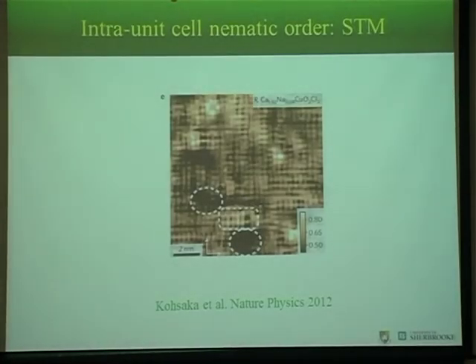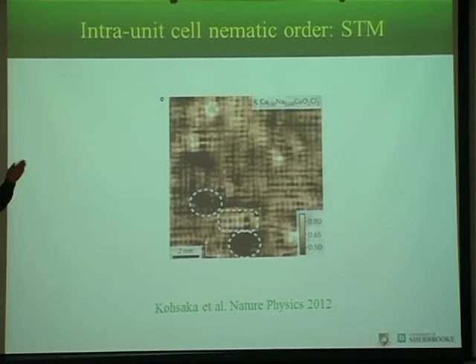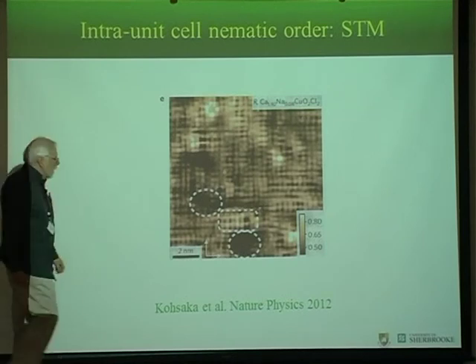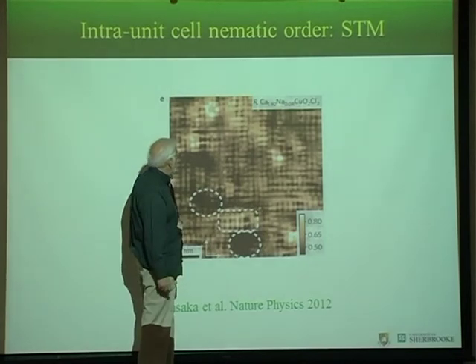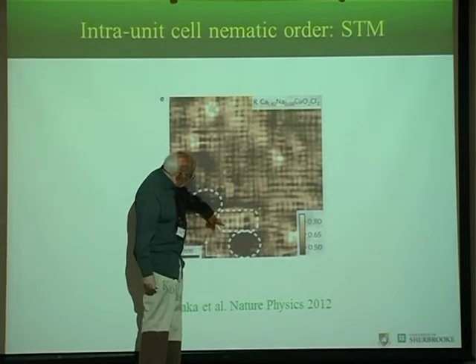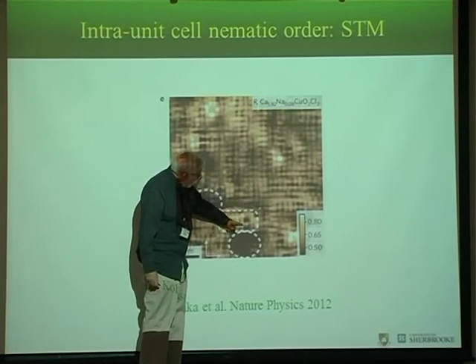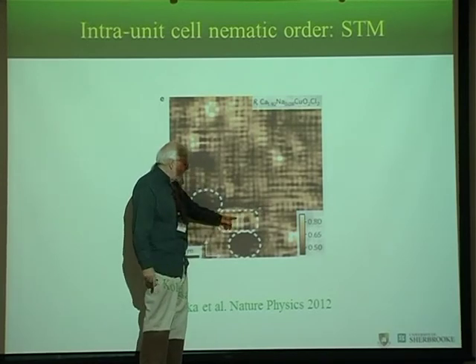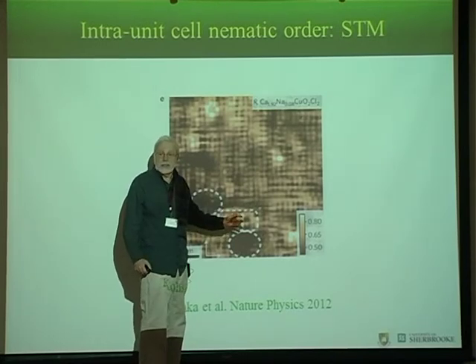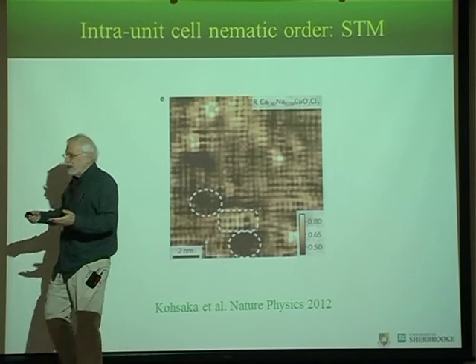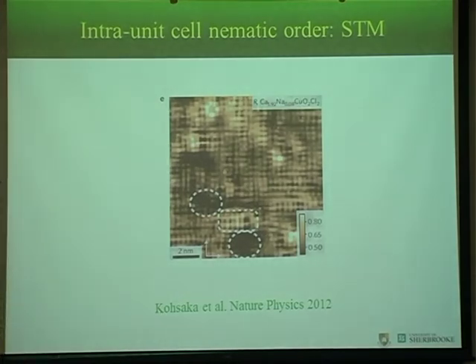Okay, now another complication. In reality, we have copper oxygen, as I said. So this is a picture from scanning tunneling microscopy from the group of Seamus Davis at Cornell. I don't have time to go through all the details, but the point is that you see that there seems to be some intra-unit cell order, and that's along the bond. So they seem to imply the oxygen. So all the discussion I had before, at least theoretically, was in this one-band Hubbard model. Here, if the oxygens are really playing an active role, it means one needs to take a more complicated model.